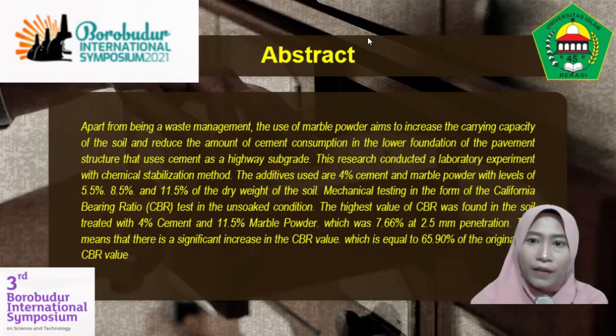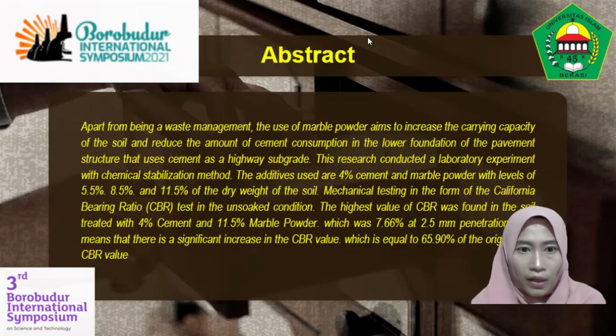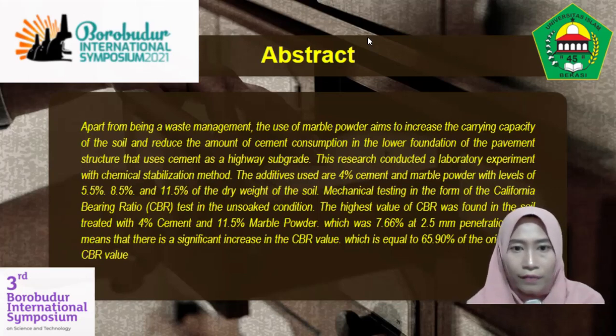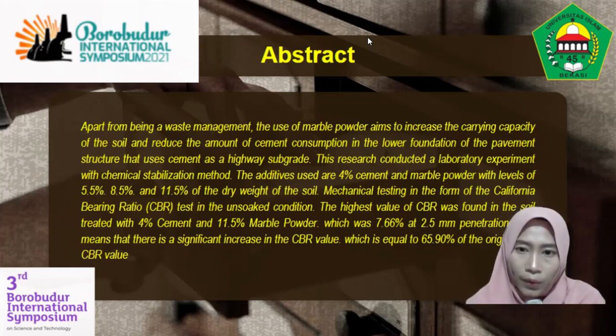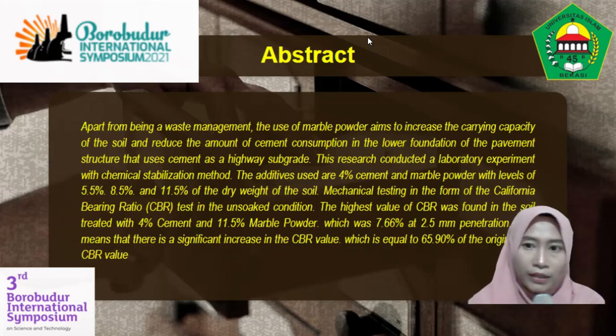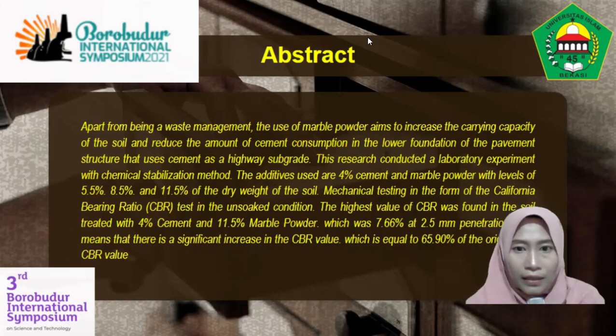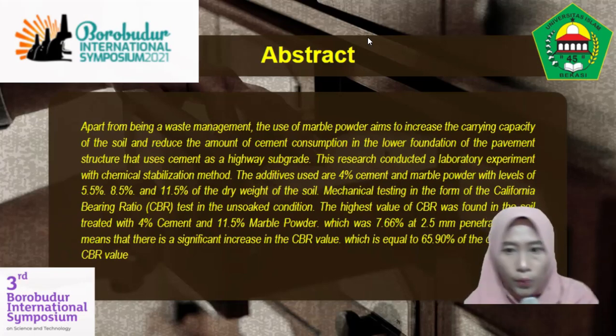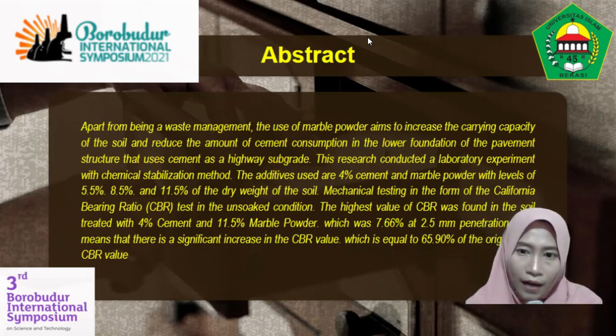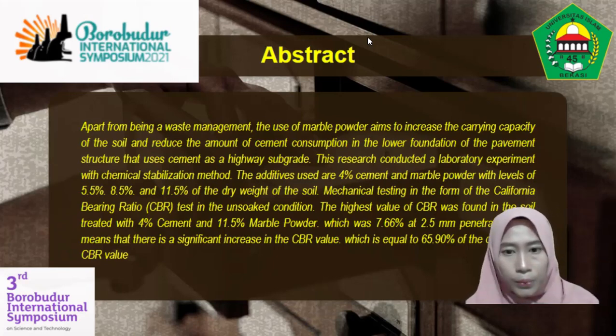The highest value of CBR was found in the soil treated with 4% cement and 11.5% marble powder, which was 7.66% at 2.5 millimeter penetration. This means that there is a significant increase in the CBR value, which is equal to 65.90% of the original CBR value.